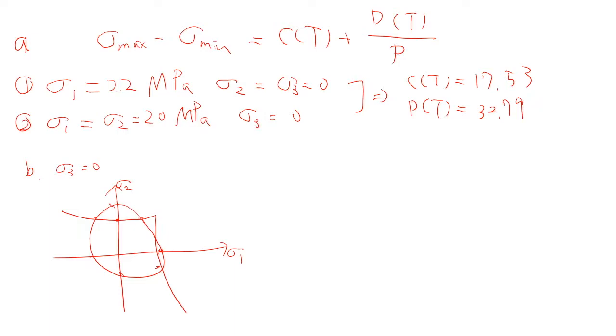When I say there's no physics, it's an empirical relationship. F equals ma is an empirical relationship too, so there is clearly physics in it, it's a rule, but there's no mechanism behind this form. There's not a mechanistic dependence. The shear banding yielding, on the other hand, comes from J2 plasticity theory.